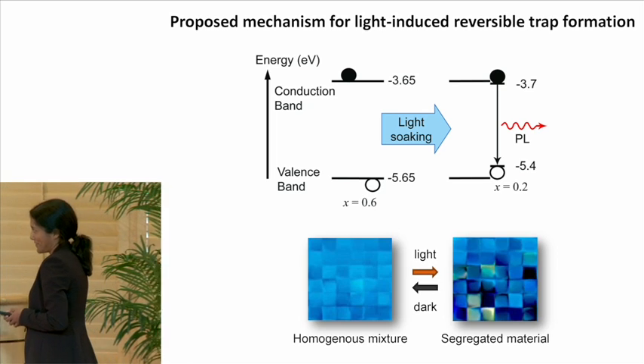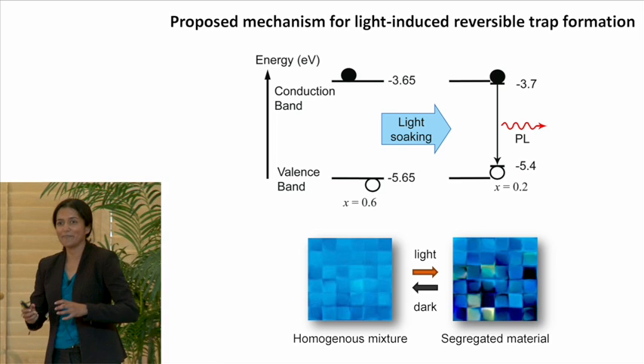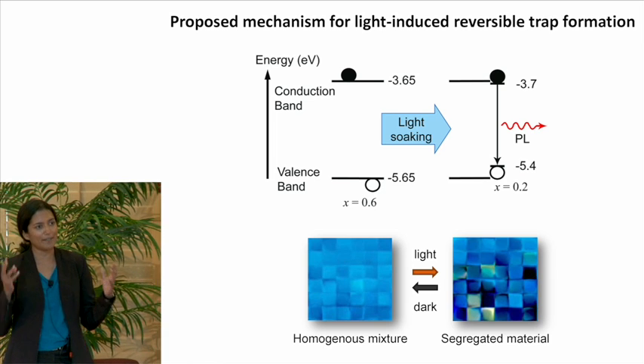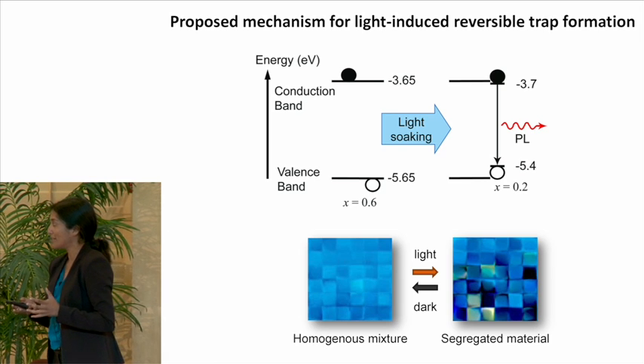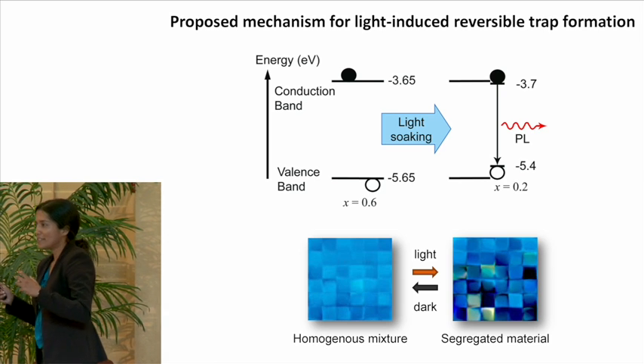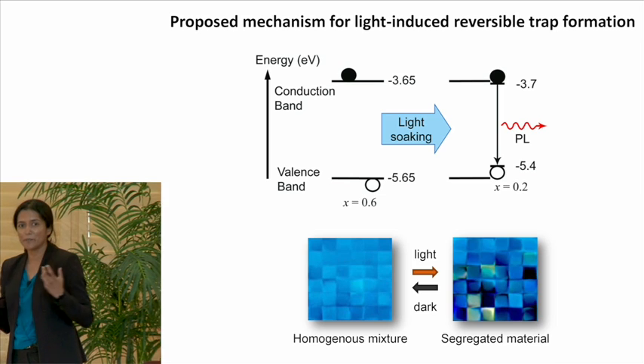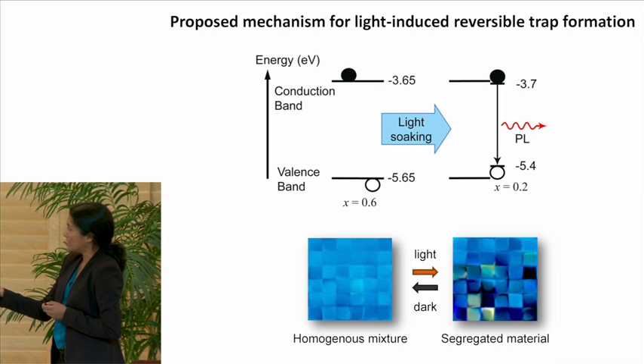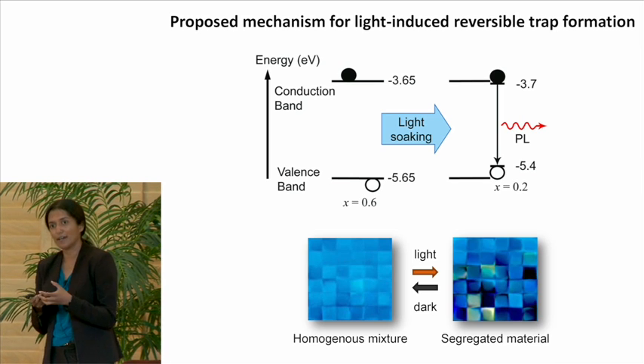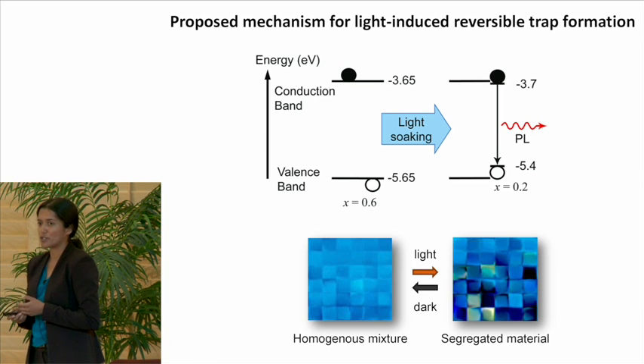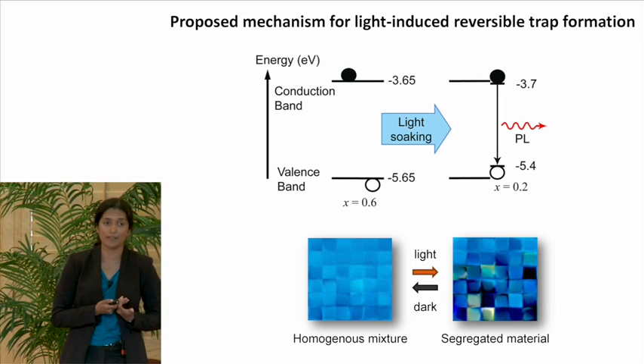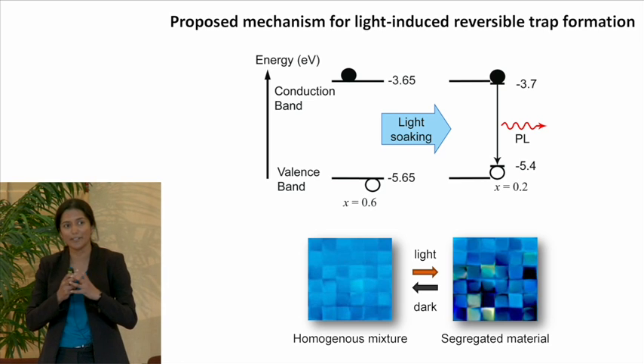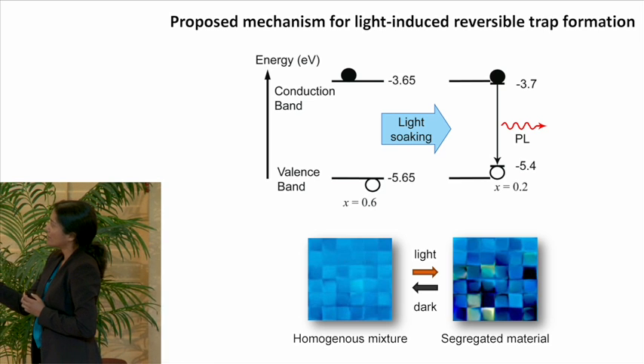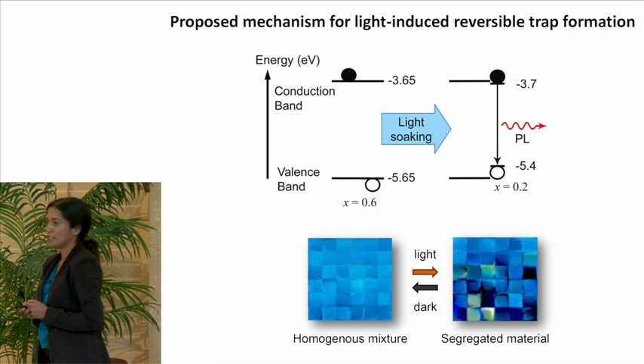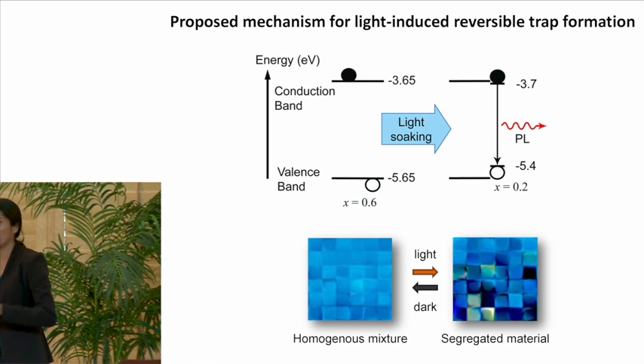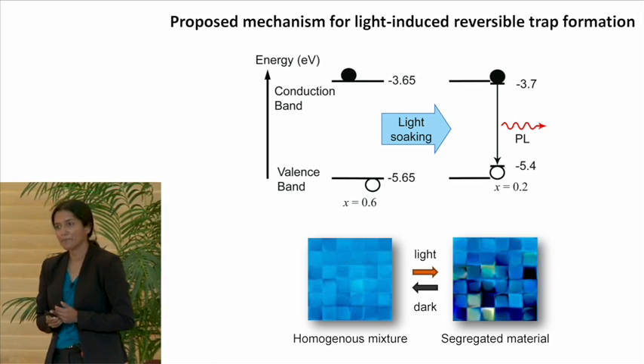So our speculative mechanism can be summarized with this picture. We have this homogeneously mixed lead bromide iodide lattice, but when we shine light on this material, there's halide segregation that is initiated by the illumination. And here, my darker blue squares show areas of higher iodide content, and these lighter blue squares show areas of lower iodide content. So there's halide segregation under illumination, and all the holes, of course, will move to the lower energy material, which is the iodide-rich material. And therefore, we get photoluminescence only from that trap.